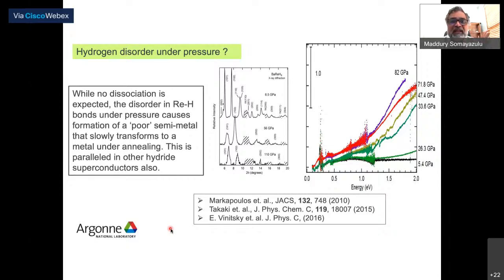Now, what does it mean? It means that as you increase the pressure, your hydrogen content may not change, but because hydrogen is such a light element, and more probably because zero-point motion becomes important, the hydrogen-hydrogen interaction gets tuned in such a way that you start forming a kind of a poor metal. What it tells you is that there is a certain amount of hydrogen disorder under pressure which will affect your transition temperatures. And I think we are coming to that situation today in that we are beginning to understand that this is parallel in the hydride superconductors, also causing a considerable amount of confusion among theorists as to what is the cause of superconductivity in these materials.